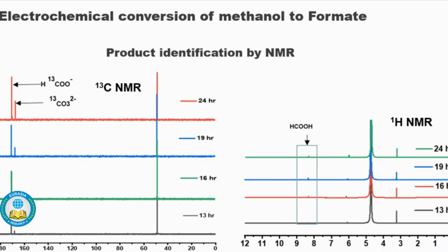And also the Faradaic efficiency of MOR was estimated to be 91% after 19-hour electrolysis, which is among the highest Faradaic efficiency of the reported electrocatalysts for MOR. Thus, the used electrolytes can be recovered through membrane separation technique to produce formic acid as a value-added chemical.